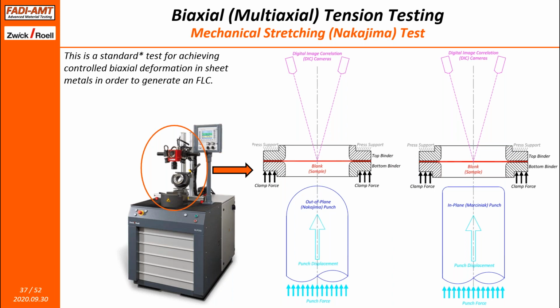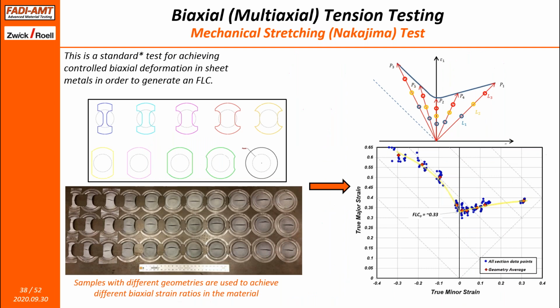These are typical biaxial tests that are performed on sheet metals in order to generate an FLC. And to give you a little bit more details about how it's done, with that particular setup that I showed, you change the sample geometry as shown here in order to achieve different deformation modes or biaxial ratios, as shown in the schematic on the top right corner. With the control of the sample, you can achieve tension, you can achieve plane strain, and you can achieve balanced biaxial. And that depends on the sample, and ultimately you can generate an FLC as shown at the bottom right corner.